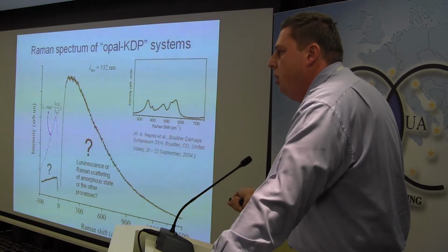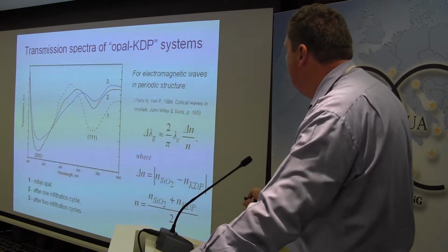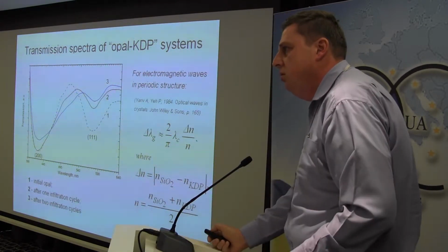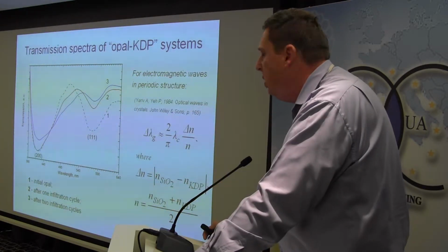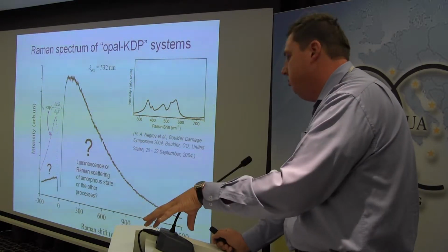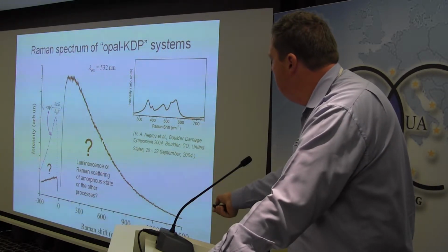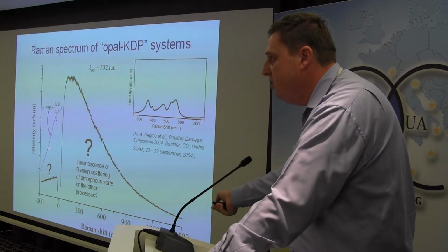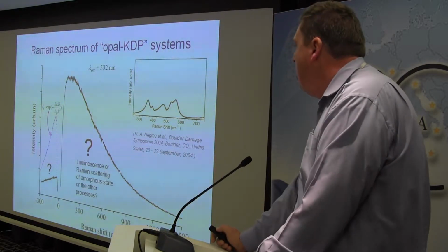Maybe luminescence. Luminescence of what? Luminescence of impurity center. We can assume that impurities. But in this case, the transmission nearby the laser line excitation in our transmission spectrum must be low. Must be low. But in our case, we don't observe this. Well, maybe it's Raman scattering of amorphous state. Maybe. But we measured the anti-Stokes spot, and in this figure you can see a simulation of the anti-Stokes spot. Here. You can see that the anti-Stokes spot in this case must be much higher than that we have observed. What is the reason? Maybe these are other processes.